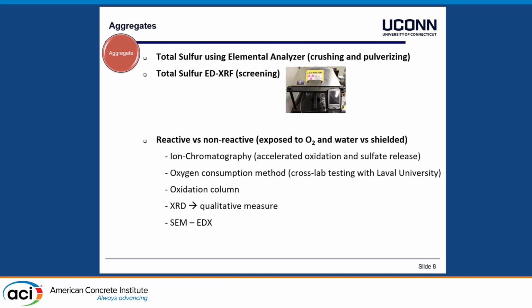So what can we do in terms of aggregates? So the Canadian research team, they had shown this with using the elemental analyzer for evaluating the amount of total sulfur once the aggregates are crushed and pulverized, so that you have accessible to all sulfur sources there. You can also use in handheld screening ED-XRF tool you see there in the picture to screen the aggregate in the field. So it gives you an idea of the amount of iron or whatever element you're screening for, or sulfur. But it's not as accurate, so it can only be used as a screening tool.